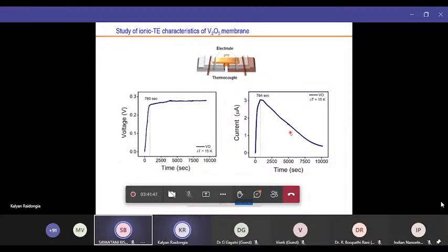We can also apply this temperature difference for a long time. You can see the voltage is almost unchanged for around 10,000 seconds. Similarly, the current is decreasing with time, because unlike electronic materials, once the ions have gone from one side to another side, they have to accumulate in some places. It gets charged. These ions cannot move to the electrodes, so they accumulate. As the ions accumulate here, they repel the incoming ions, and no new ions are generated here. So there will not be sufficient ions to move from this side. So the current decreases with time, but the voltage remains constant with time.